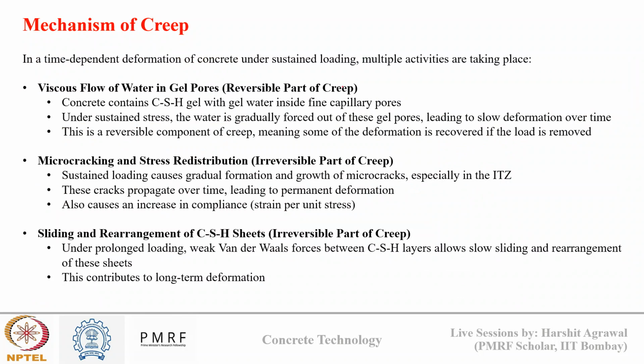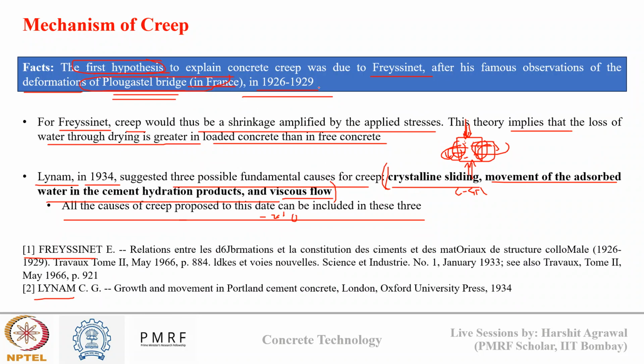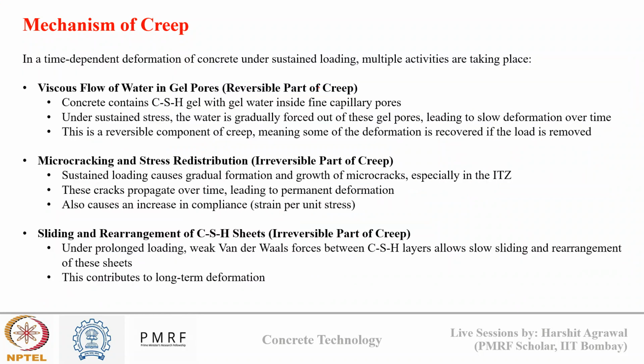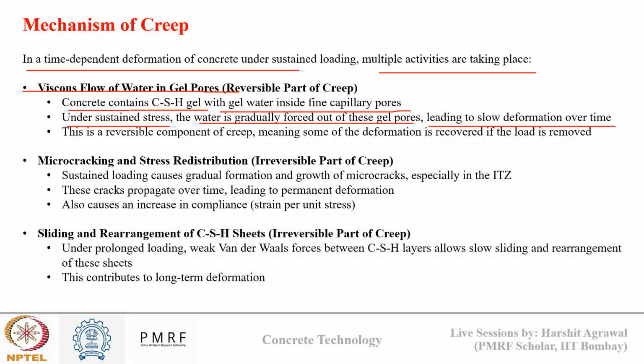So if we try to understand the second theory, the Lynam theory, who says that there are three possible causes of creep. What he says is that in a time dependent deformation of concrete, there are multiple activities that are occurring. There is viscous flow of water in gel pores. Okay, so we know concrete contains CSH gel, and there is gel water inside the capillary pores. So under sustained loading, this water gradually is forced out of gel, and loss of water from the gel pores causes deformation over time. Okay, and this is one of the reasons of creep in concrete.